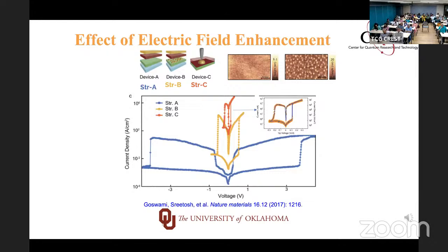Here, for example, flat electrodes, device A. When I go to device B, in the bottom electrode, I put some gold nanoparticle, so I enhance the field in the bottom electrode. Now the third device C has not only a gold nanoparticle at the bottom, but I also bring a conducting AFM tip from the top. So now the fields are really enhanced right here.